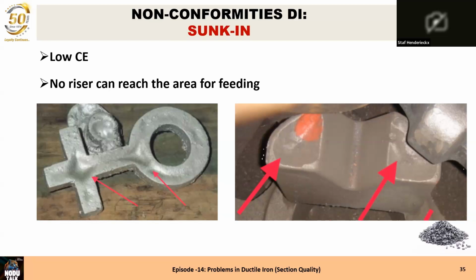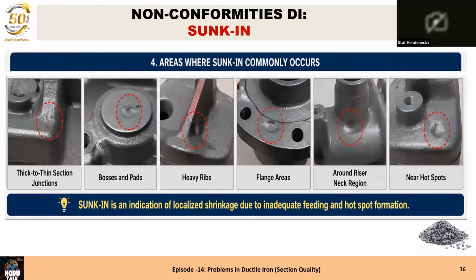Because to get a solidified layer at the outside in contact with the mold, it needs a CE lower than 4.3, because then we first get a layer building and later the nodules come out. Where you get it: in thin to thick junction sections, in bosses, mainly in bosses, in heavy ribs, in a flange, but mainly when there is a thicker area around a riser, but not that much.